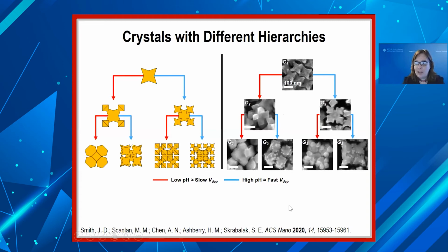Now at this point, we get a little bit of crowding, but you can still see the general trends that at fast deposition conditions, we end up with many branches that are emerging from each of the many different tips of our initial seeds. Whereas under the slow deposition conditions, we end up with more polyhedral forms forming. But here you can see we've just increased the size of the polyhedra, whereas in this version, where we have so many different growth positions, we initiate many more smaller polyhedra.